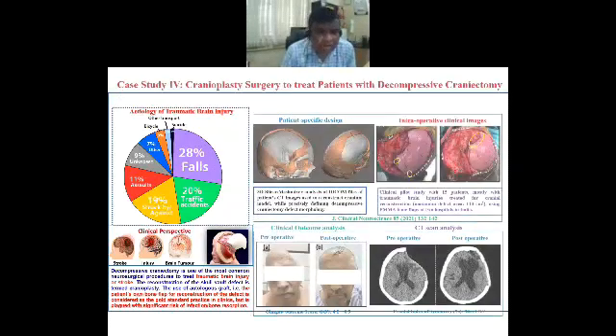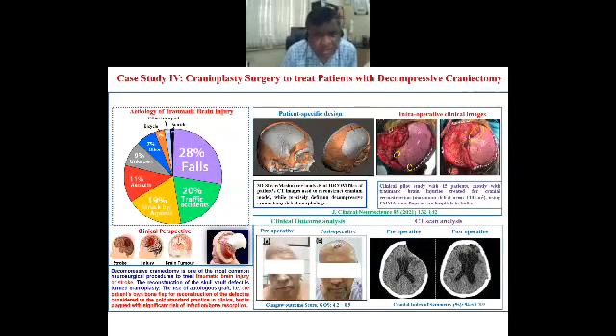What we have done is, for a number of patients, we have taken the CT scan data and identified the cranial defect area, both in terms of the area as well as the size or thickness of the plates. Then we made polymethyl methacrylate, which is a regulatory approved material. We have cast this polymethyl methacrylate into a 3D printed cranium skull.